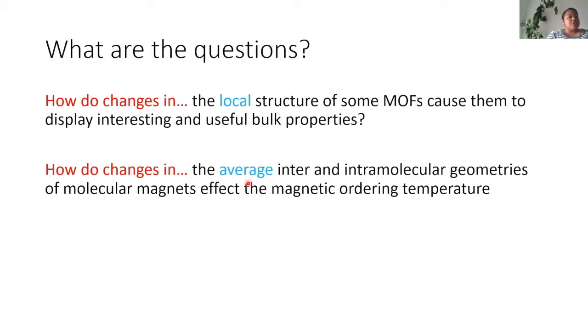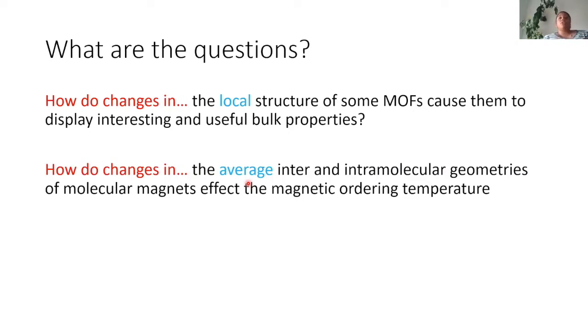If that's the question, what's the best tool? I want to perform total scattering experiments - how about I-15 or XPDF at Diamond? But if the local structure I'm interested in contains a lot of hydrogen, X-rays might not be the best tool for the job. X-rays interact with the electrons of an atom, so the more electrons you have, the bigger you appear. When collecting and analyzing X-ray data, it's often difficult to see lighter atoms as the diffraction pattern is dominated by contributions from the heaviest atoms in the system.